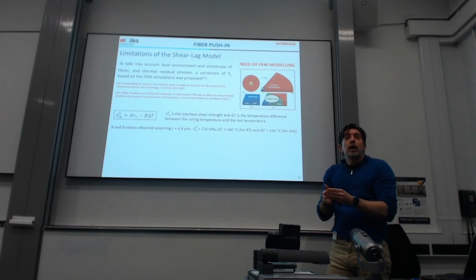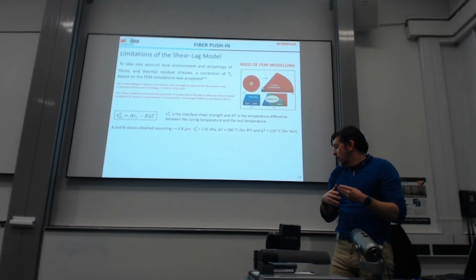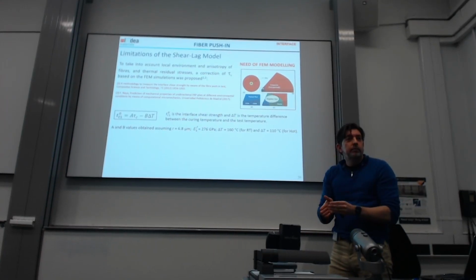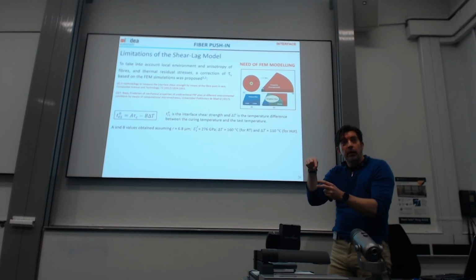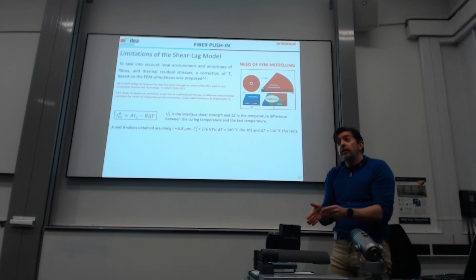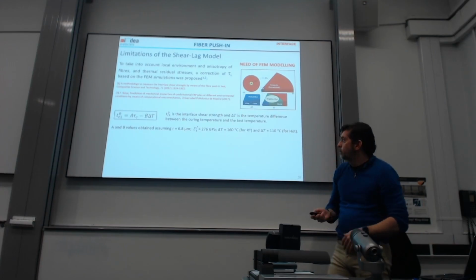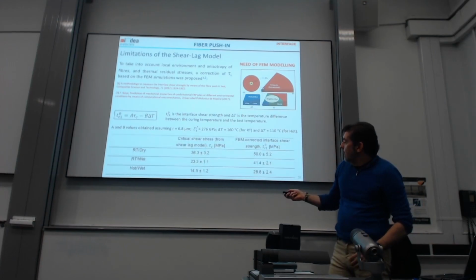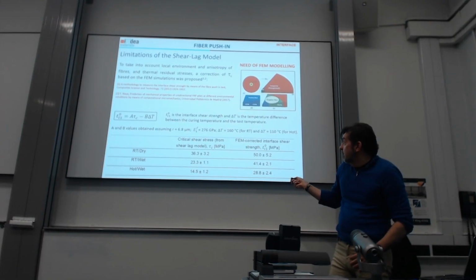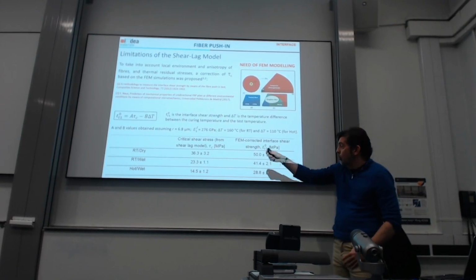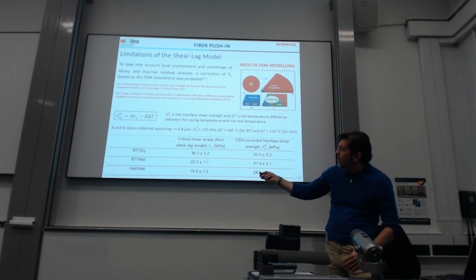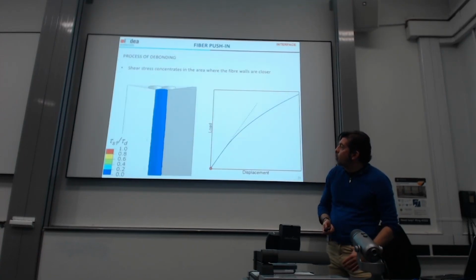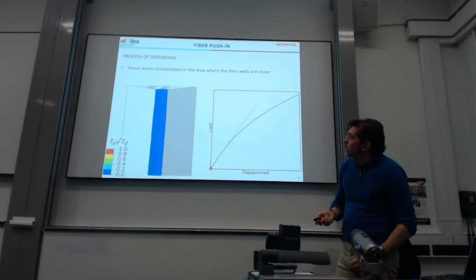These are unidirectional fibers. So with this hexagonal configuration, you make sure that it's more likely that the interfaces are sort of perpendicular. And at the end, you get the corrected shear strength by using this formula. This A and B depend on the radius of the fiber, modulus, and this delta temperature. This is some simulation that some people have done.